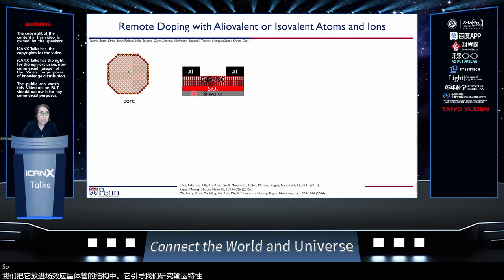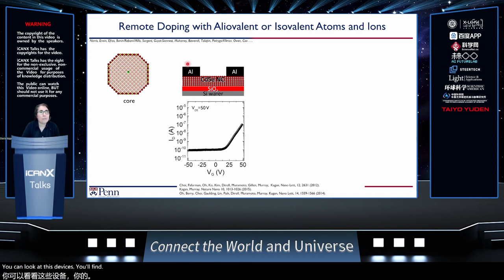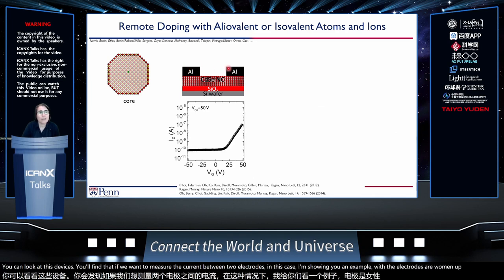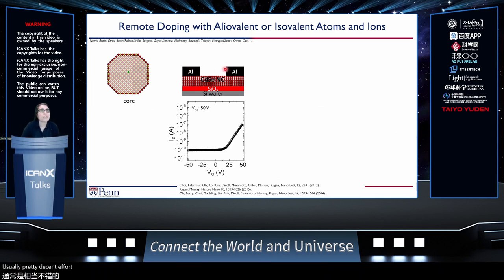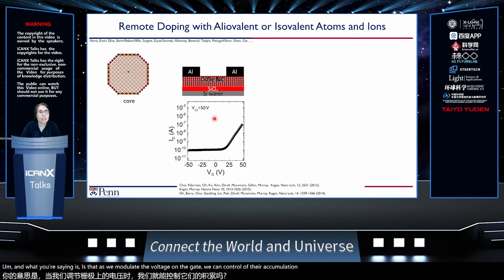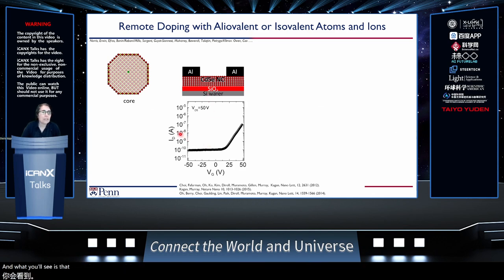So if we look at these devices, we want to measure the current between two electrodes. In this case, the electrodes are aluminum. They're usually pretty decent for getting charge into and out of some material that's N-type, which is what the cadmium selenide is. What you'll see is that as we modulate the voltage on the gate, we can control the accumulation of electrons in the channel. And as you look at the current versus gate voltage characteristics, at positive voltage, characteristic of an N-type material, there's an increase in the current, but it's not that impressive, right? It's not something that we would get excited about in building devices.